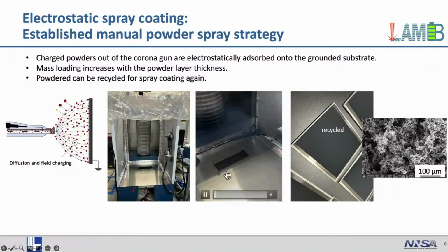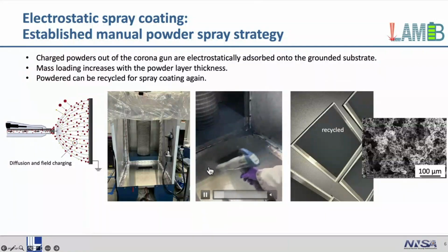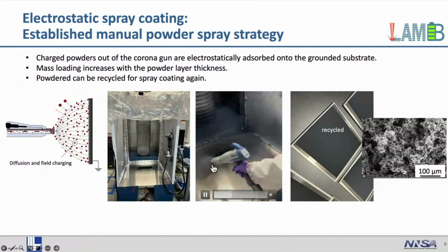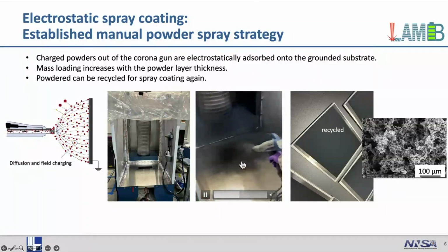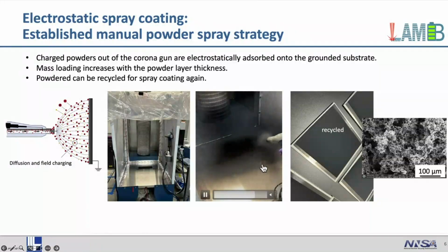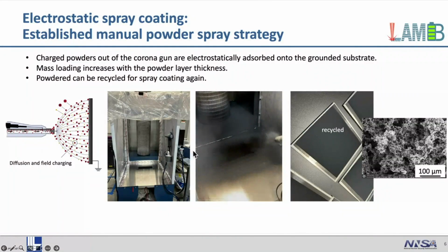And this is a layer of the aluminum foil laid down on the floor. And we can do spray coating on there, multiple passes, and then you can get a relatively uniform coating after that. And those powders that are surrounding there can be recycled and reused in the spray, and that also shows consistent powder coating uniformity.